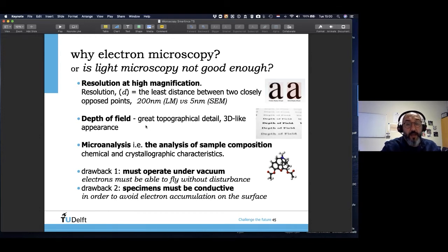Microanalysis is another thing. If you remember, I mentioned birefringence and seeing special colors under cross-polarized light modes in the optical microscope. That gives us chemical information. But with electron microscopes, we can go even deeper and more detailed. We can get an elemental composition and compositional distribution of our microstructures thanks to the characteristic X-rays that are developed from your microstructure. So these are the advantages of electron microscopes over optical.